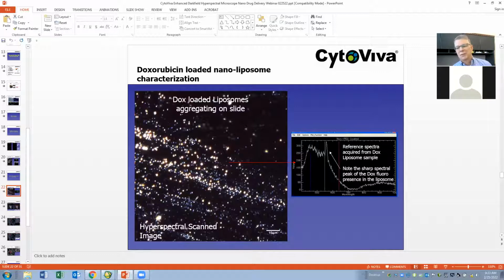So here we're looking at DOX-loaded liposomes, and a representative optical spectrum of the doxorubicin-loaded liposomes. You see this really sharp peak in the spectrum. DOX is known to have a natural fluorescence in the late green, yellow, early red area. And so we see this sharp peak that appears consistently in these doxorubicin-loaded liposomes, with a peak optical spectrum here at about 585, 590 nanometers.